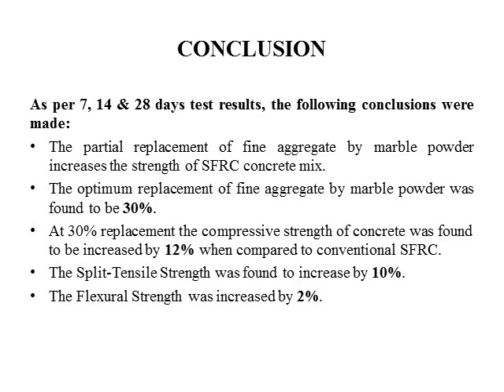Conclusion. As per 7, 14 and 28 day test results, the following conclusions were made. The partial replacement of fine aggregate by marble powder increases the strength of SFRC concrete mix. The optimum replacement of fine aggregate by marble powder was found to be 30%. At 30% replacement, the compressive strength of concrete was found to be increased by 12% when compared to conventional steel fiber reinforced concrete. The split tensile strength was found to increase by 10%. The flexural strength was increased by 2%. Thank you.